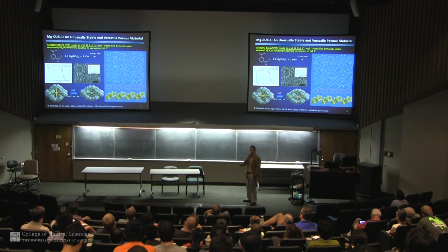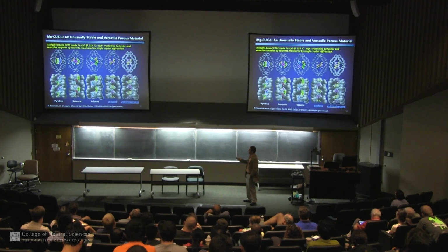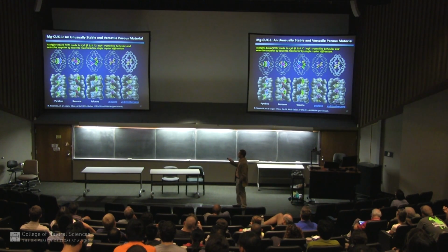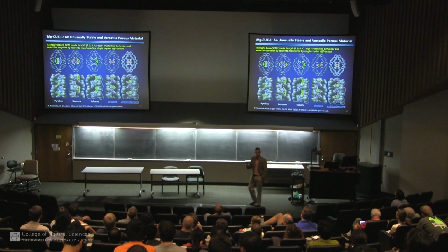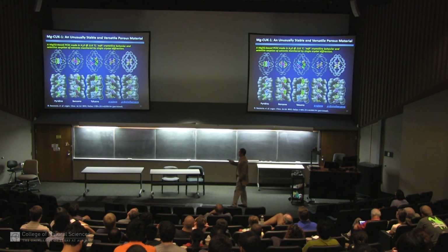And we can dip these crystals into a range of solvents, and the solvents load the pores. Maybe not surprisingly, but when I show this picture to most people, they think now this is a model because people are commonly modeling solvents in the pores. These are all single crystal structures. We take the crystals, dip them in the solvents, and then we can do crystallography again and find where the solvent molecules are sitting inside these pores, which is quite remarkable.